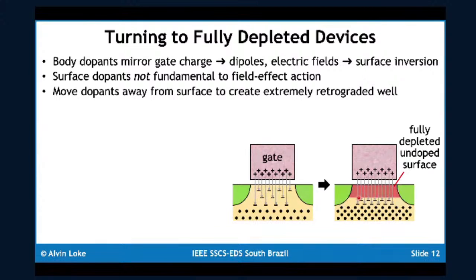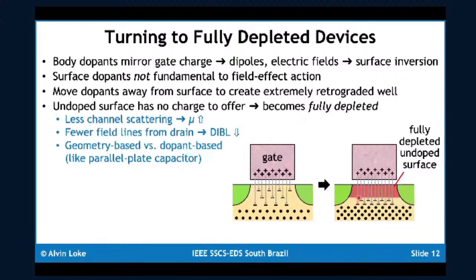And this actually has a bunch of advantages. Number one, because you have, in principle, no dopants in this fully depleted layer, you basically have much less channel scattering because you don't have the ionized dopant impurity scattering, which causes your mobility to go back up.